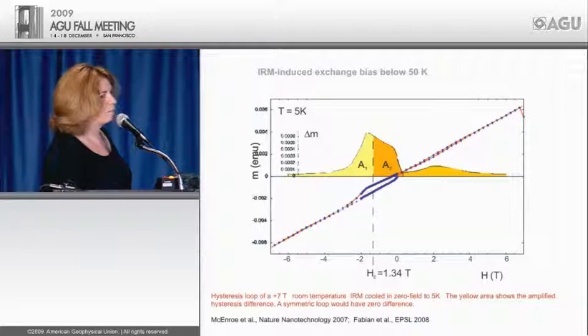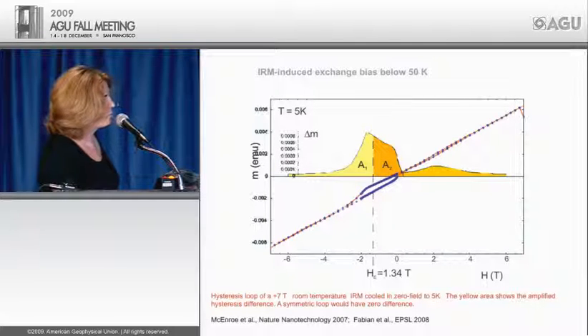Now this is the largest shift that's ever been found in any material, natural or synthetic. And the only one that was close to this was actually found back in the 50s. It's a cobalt-cobalt oxide. So understanding the nature of this coupling, how do you get material that can do this, is something that will be used to try to make templates for future devices. But it's been very hard to study in this field. People have had a hard time explaining how you get shifted hysteresis loops, and there are thousands of papers on this.